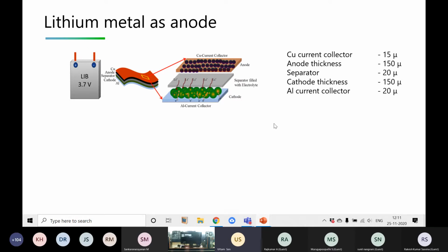So just look at this, the standard electrode of any cell. Okay, so we have a current collector, a copper collector for the anode, then anode material, then separator, cathode material, and this aluminum current collector for the cathode. So if you look at their sizes, the thickness: copper current collector is around 15 micron, anode thickness is around 150 micron, separator is around 20 micron, cathode thickness is around 150 micron, and similarly the aluminum current collector is around 20 micron. This is a ballpark number, the number could vary. Okay, this is how the cell is fabricated.